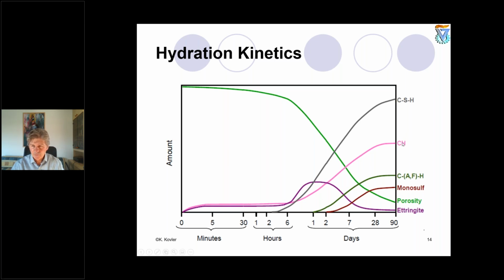Different phases are formed in parallel to the main strength-bearing phase, CSH: calcium hydroxide, which is responsible for alkalinity, which is a nice thing from the point of view of protecting the steel reinforcement from corrosion. We have other phases, monosulfate, ettringite, and many others.